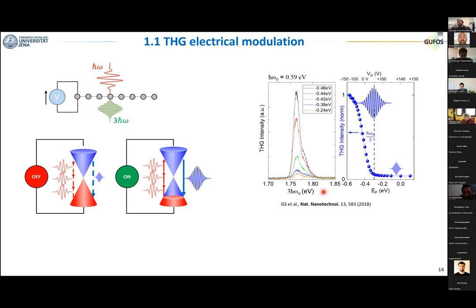It is a very good point, but I would go back to the theory of nonlinear optics in general. The fact that you can have an enhancement when you are at resonance is true for any material, and indeed the materials that are used for nonlinear optics typically, like BBO, KTP, periodically poled crystals, must be fully transparent.